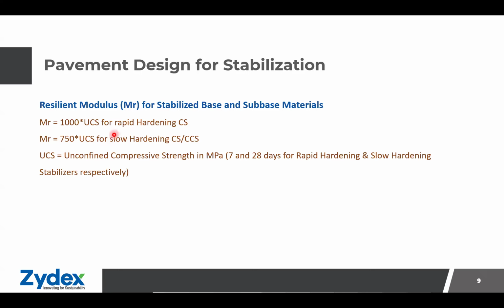For a rapid hardening, the guidelines suggest to use a multiplier of 1000 multiplied by UCS. That will give the resilient modulus for the base layer with a rapid hardening CS. For slow hardening CS or CCS, the guidelines suggest to use a multiplier of 750.